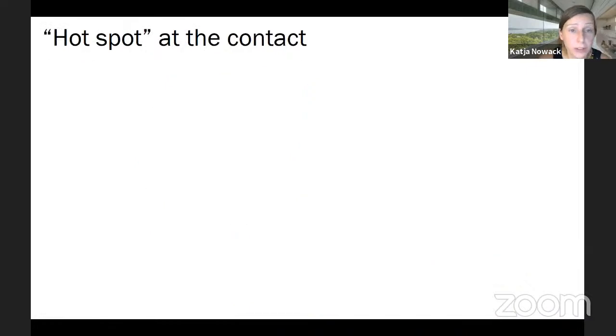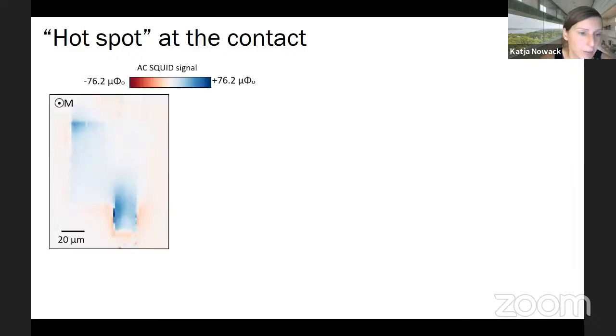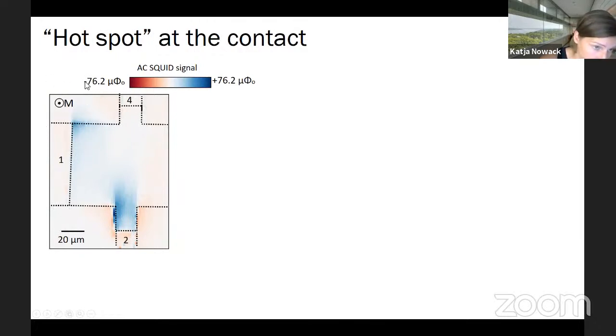Okay, what we can also do is take an image of how the current enters the device. And what is interesting to see is that we actually see hotspots at the contact. So now, let me see. Now you see the outline of the Hall bar here. This is the wide source contact that we use to send current into the device. If the magnetization points out of the plane and we take an image, then we can see the current enter the device in this corner.